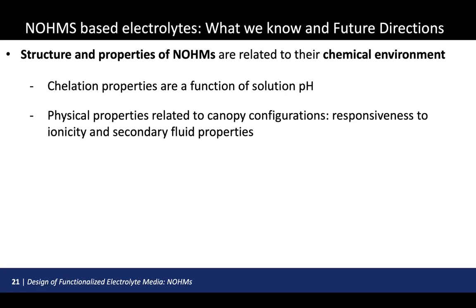It's quite easy to tune that, because when we synthesize the NOHMs, we can change the amount of polymer we tether onto these by changing the grafting density. And of course, there's a limit given by the surface area of the particle. So in terms of increasing, there's a limit, but we can definitely go lower. And then in terms of the number of chelating sites on the canopy of the polymer, we can increase the number of chelation sites by increasing the molecular weight of the polymer. But that will lead to inherent challenges related to even higher viscosity and less flowability, etc.